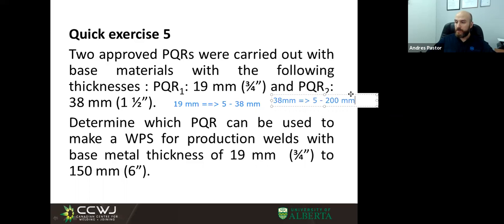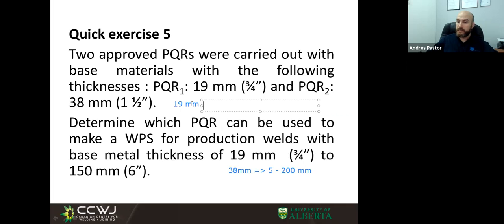So in this problem, we had to determine which PQR can be used to make a WPS for production welds between base metal thickness of 19 millimeters to 150 millimeters. This qualified range, the first PQR, for example, doesn't cover this range of base metal thickness. Okay. However, the second PQR covered this range of base metal thickness. So the answer is the second PQR. So the second PQR can be used.